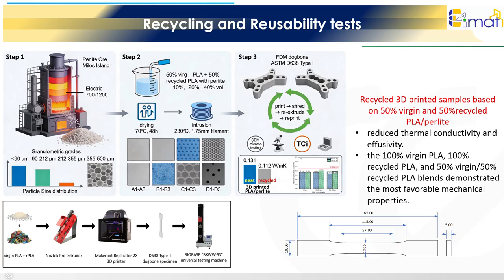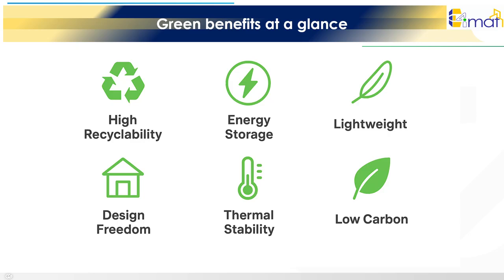3D printed samples based on 50% virgin and 50% recycled PLA perlite indicated reduced thermal conductivity and effusivity. The 100% virgin PLA, 100% recycled PLA, and 50% virgin 50% recycled PLA blends demonstrated the most favorable mechanical properties. To conclude, this 3D printed cladding system brings together all the essential features of next-generation green building materials.